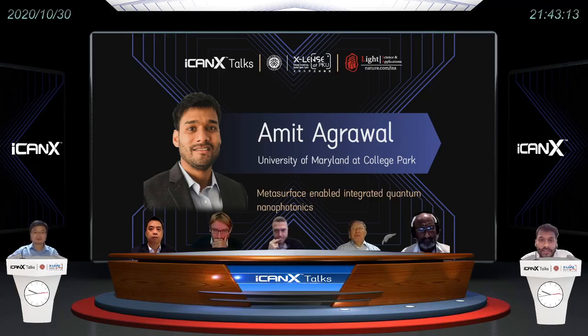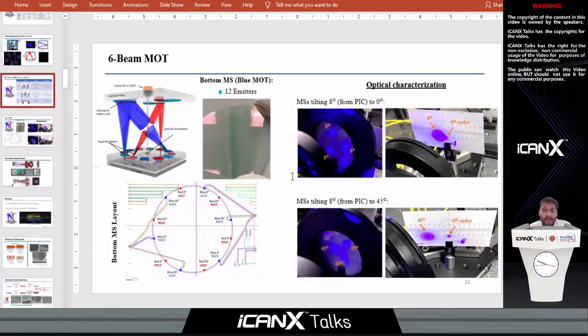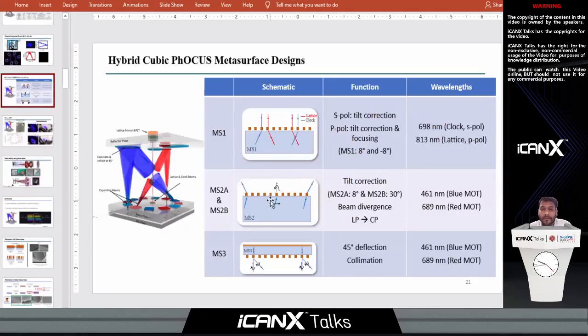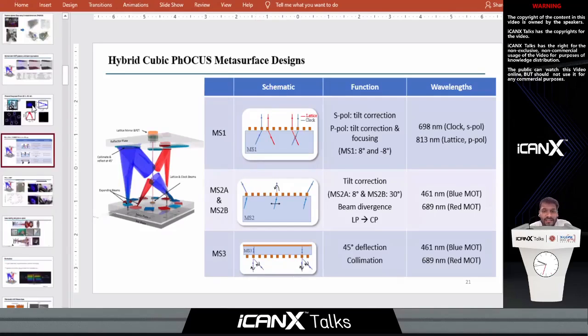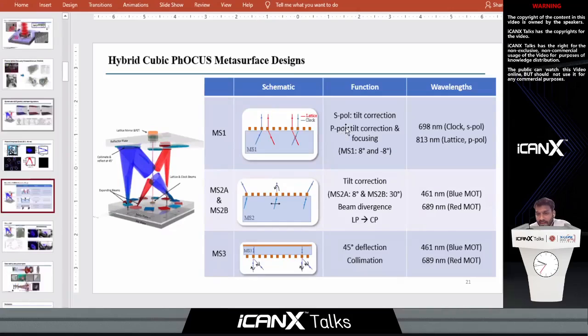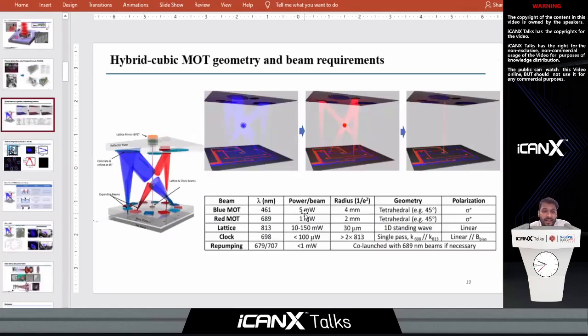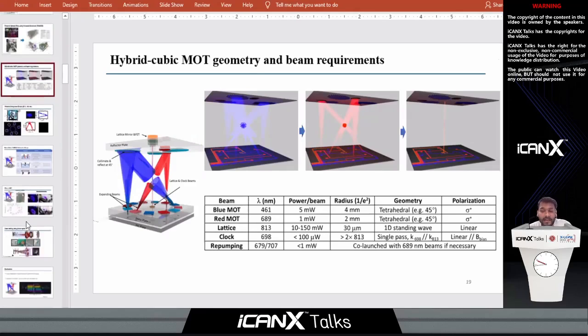So the efficiency for, let's say, a meta surface that looks like this, a multifunctional one, is in the order of 70 to 80%, which is typical for all meta surfaces that we work with. Even the reflector that is shown here, we are getting efficiencies around 70 to 80%. But what is I guess more important is that this is the beam power that we need at the atom location. Otherwise, we won't see atoms, right? And if we use decently enough powerful laser beams, then this 60 to 80% efficiency numbers are acceptable. But maybe for some applications it may not be, right? At least for this program, it is quite acceptable.